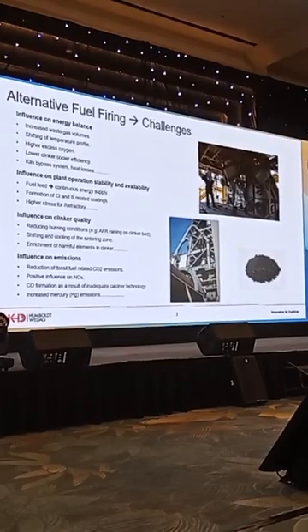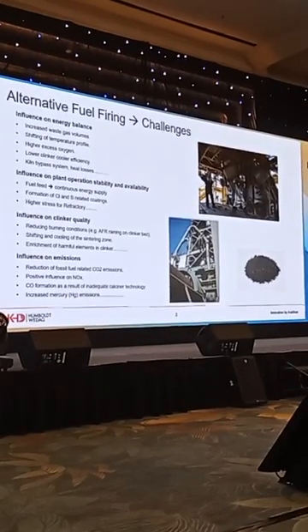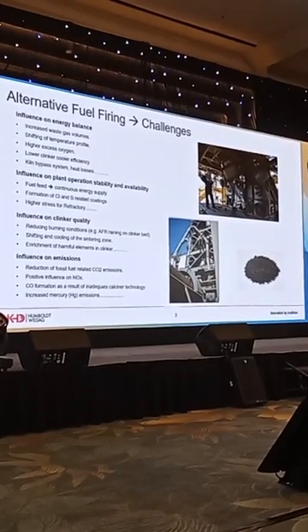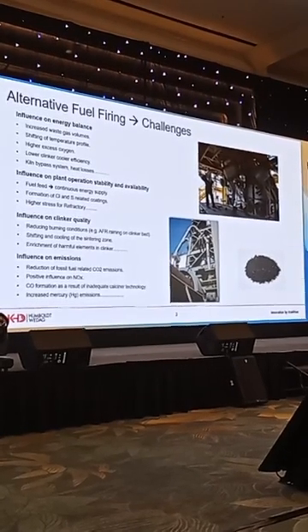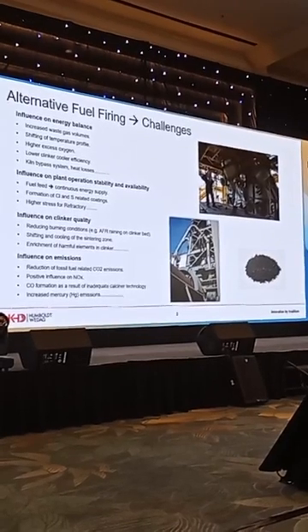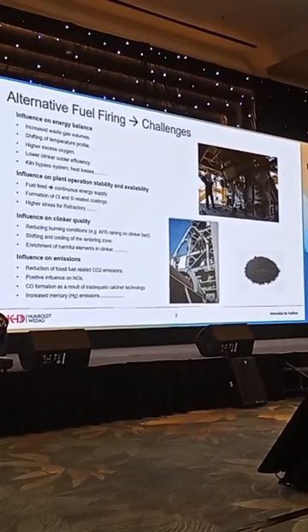Also, when you want to burn alternative fuels, you need higher oxygen for the burning itself. This means not only 2-3% oxygen at the kiln inlet or behind the calciner will be sufficient. There we are talking about 1% more maybe.